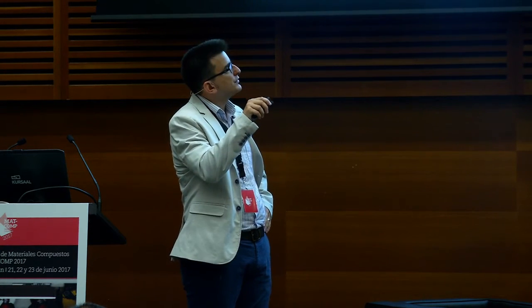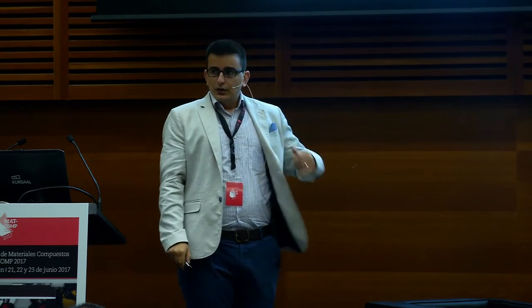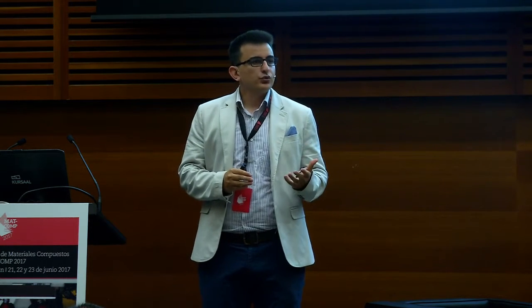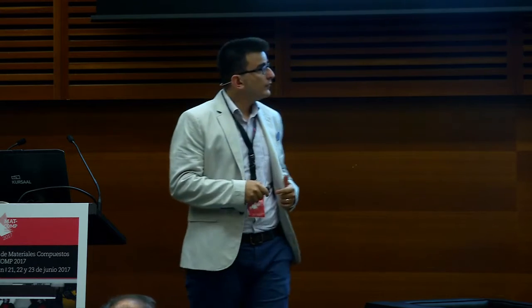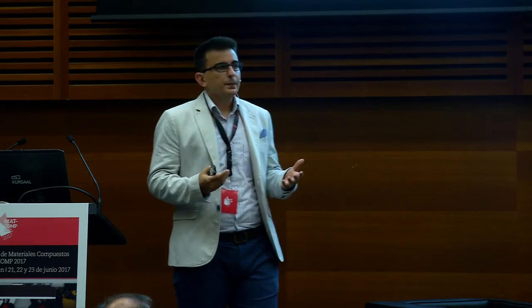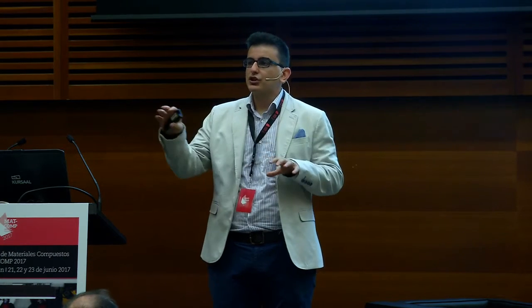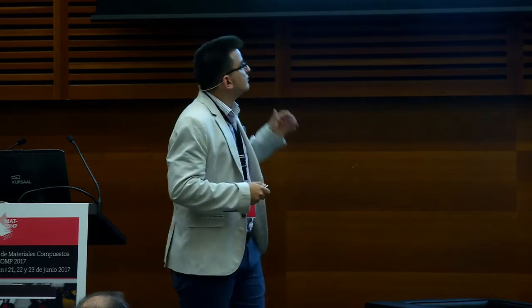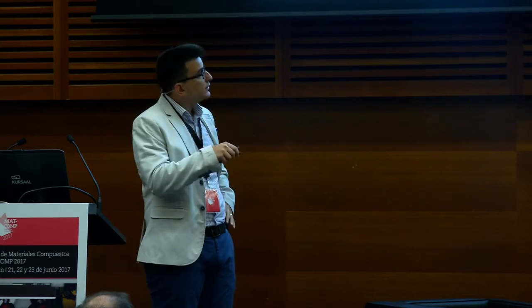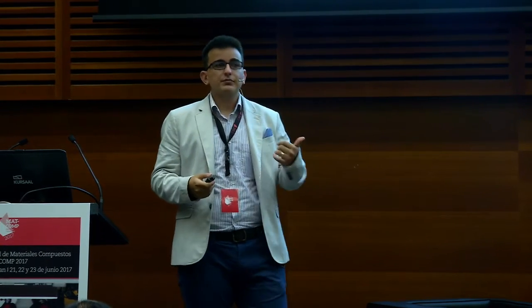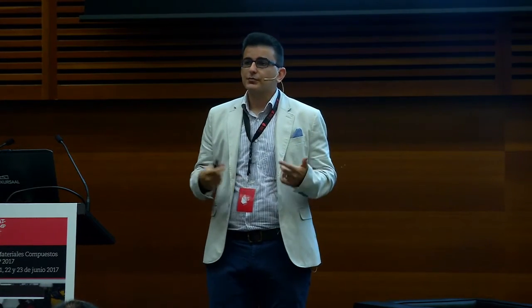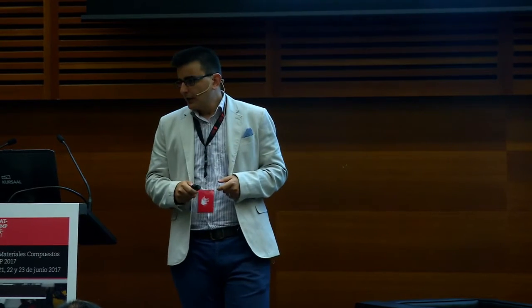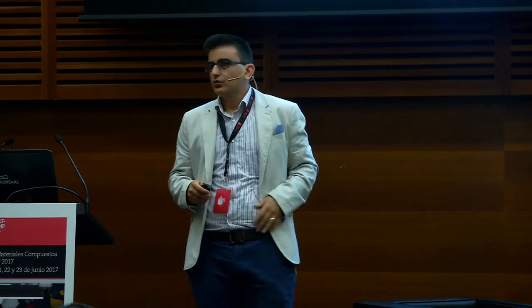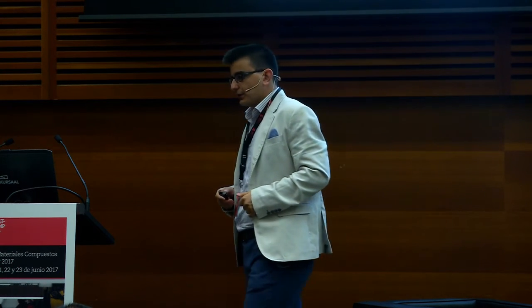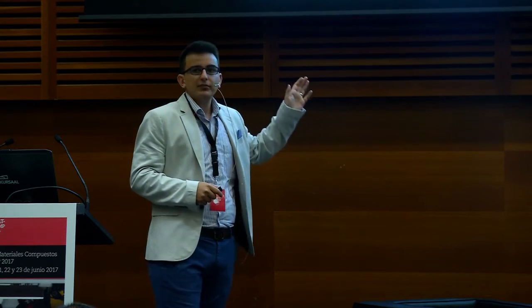So here we have the nip point temperature between the tape and the substrate. We would like to calculate the nip point temperature in a fast and accurate way such that we can control the process inline. With the predictions using the model, we can provide optimum process parameters to the machine, and the machine controls the process for improved bonding quality. Because the bonding in between the tape and the substrate is heavily dependent on the temperature, as well as the contact pressure, intimate contact, and healing, and so on. Other than this model-based inline process control, it's obvious that we can do offline process optimization using deterministic and reliability-based approaches.